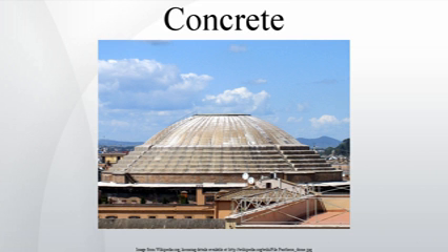The record for the largest continuously placed underwater concrete pour was completed October 18, 2010, in New Orleans, Louisiana by contractor CJ Mahan Construction Company, LLC of Grove City, Ohio. The placement consisted of 10,251 cubic yards of concrete placed in a 58.5-hour period using 2 concrete pumps and 2 dedicated concrete batch plants. Upon curing, this placement allows the 50,180 square foot, 4,662 m2, lock to be dewatered approximately 26 feet, 7.9 m, below sea level to allow the construction of the IHNC GIWW Sealant Monolith project to be completed in the dry.